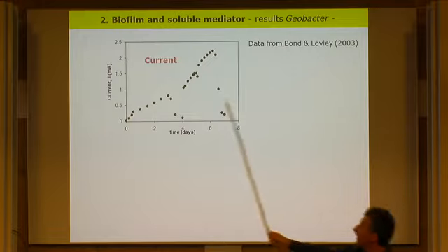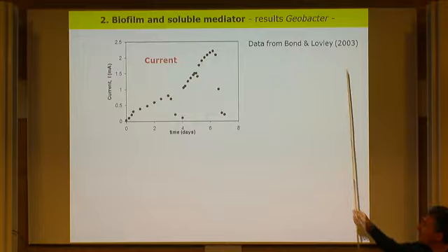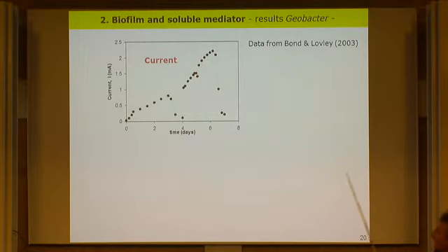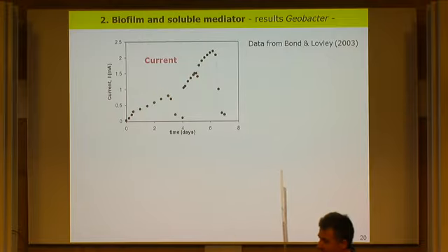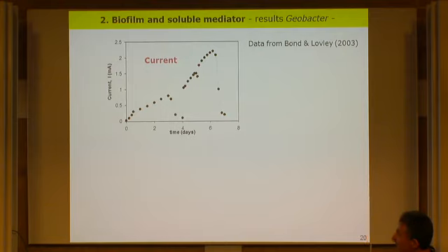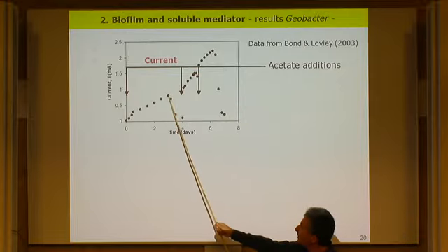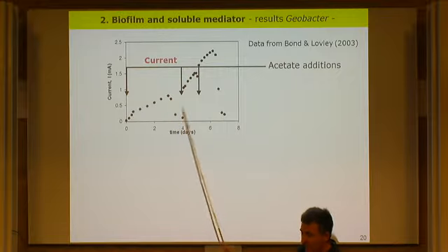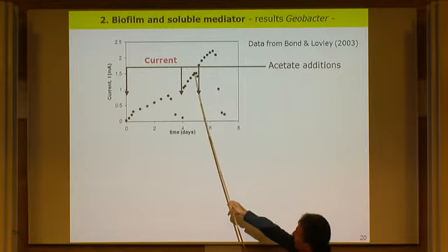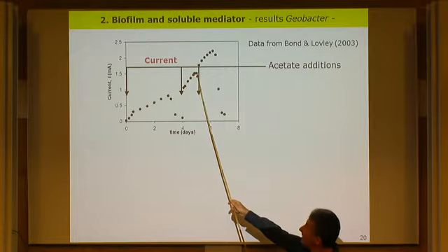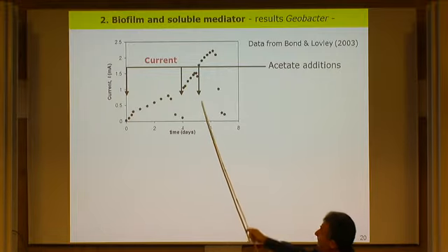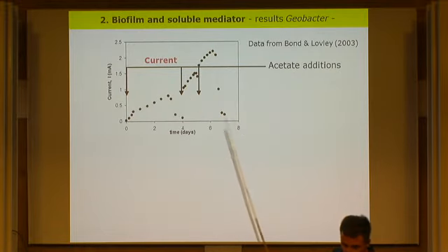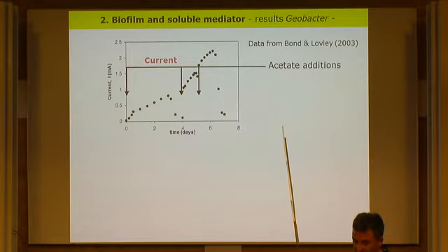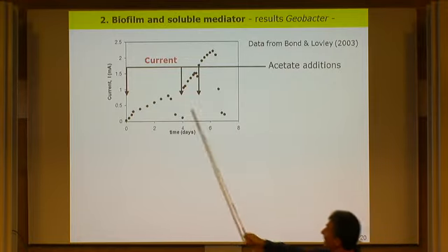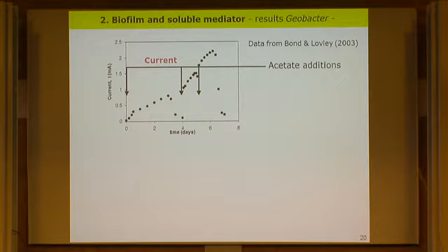And these are some famous experiments performed about 10 years ago in Derek Lovley's group. They had this Geobacter biofilm consuming acetate, and they added acetate when they observed there was no more current production. This time is with biofilm, and you see here how the current actually increases after the second addition. And then it drops because there is no more acetate, and it increases again, which means that these cells grow now. They form a biofilm, the red biofilm of Geobacter, and the current increases after each addition.